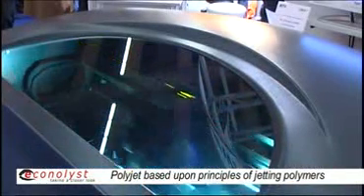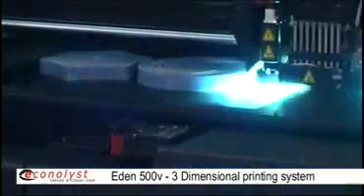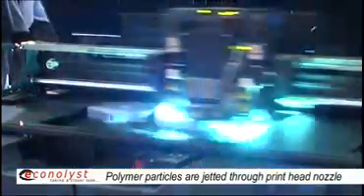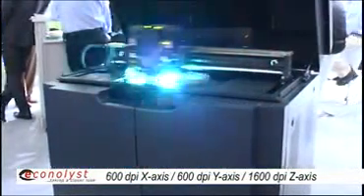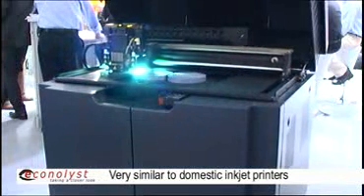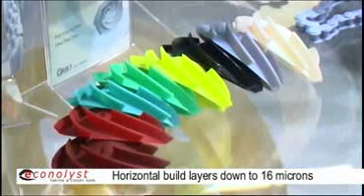What we do: we have polymer coming in cartridges in a liquid state. The polymer is jetted through a network of pipes and pumps. We eventually bring them to a piezo that, with a pulse, puts hundreds of droplets — thousands of them from each nozzle — to create a part. The heads from which the jets are jetting the photopolymer have UV light on both sides. So immediately after jetting the photopolymer, the UV light cures it instantaneously, so it becomes solid, allowing you to put the next layer. The layer is only 16 microns thick, and that enables us to get these smooth results with this technology.